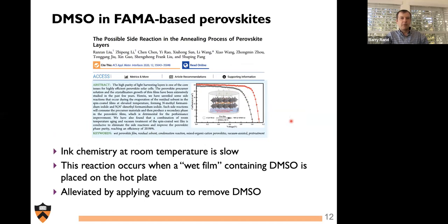And what this group showed was that the act of having DMSO left behind in the film upon annealing leads to this formation. This means this doesn't have to happen in the ink. This can happen as a result of having some remnant DMSO behind. The way that they alleviated this problem in this work was to employ this sort of vacuum process before and perhaps also during the annealing step to better remove DMSO from the film.